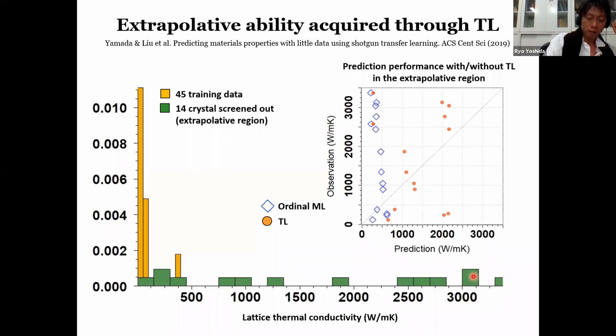This slide shows the prediction results for the 14 crystals that we identified, with respect to the results of experimental validation. As you can see, except for a few materials, the predicted values of our transferred model exhibit good agreement with the experimental observations, even in such an extrapolative region of the target.